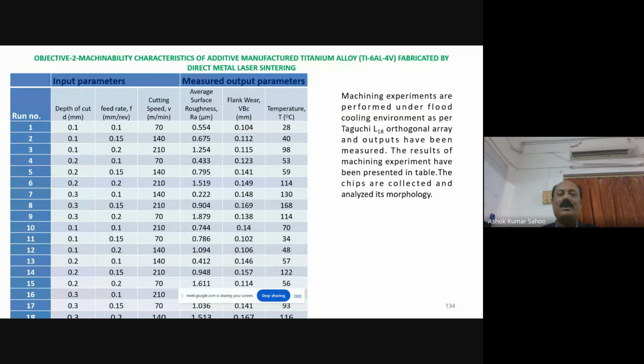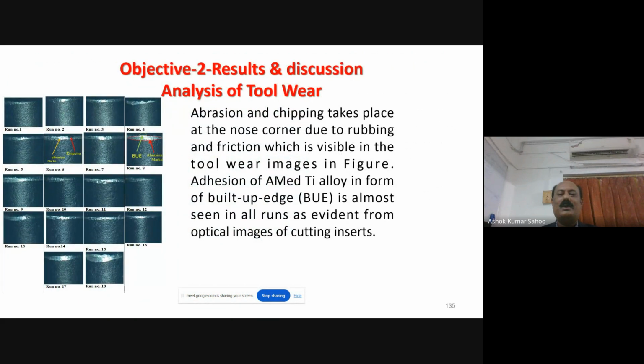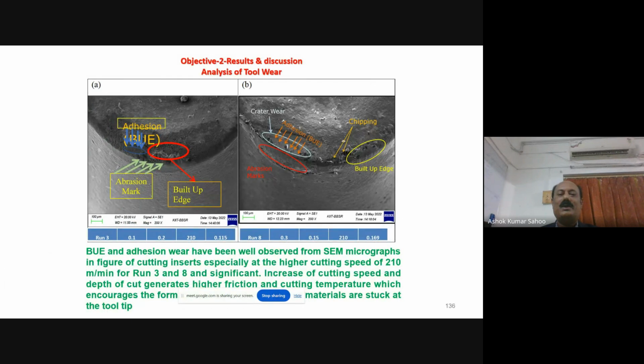Then we also conducted the machining of the additive manufactured titanium alloy and compared the result with the raw titanium alloy. We got built-up edge formation in the optical microscopic image of the flank wear region of the cutting insert after machining, carried out under an L18 Taguchi orthogonal array under flood machining environment. Interestingly, built-up edge formation is seen in almost all the runs, as evident from the optical images. Adhesion, abrasion marks, built-up edge, crater wear, flank wear, and chippings are quite observed in machining of titanium alloy.